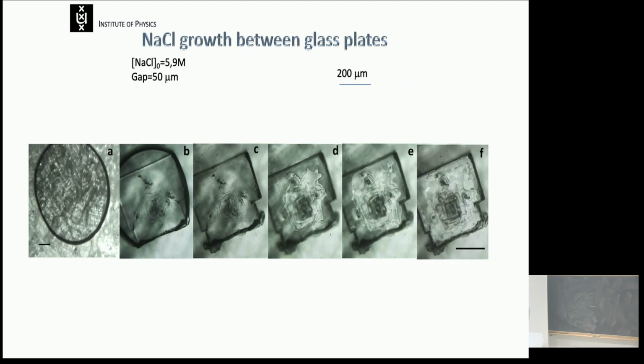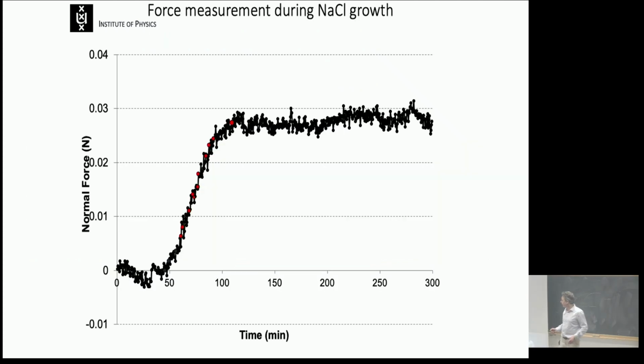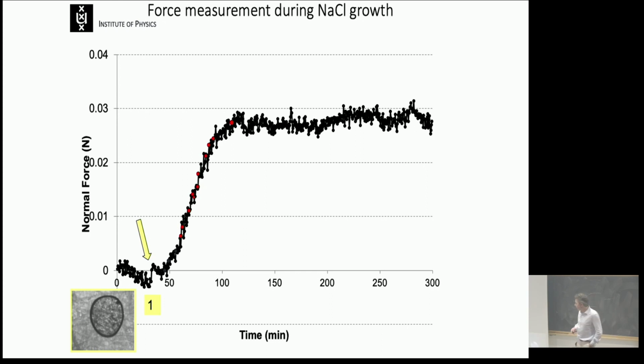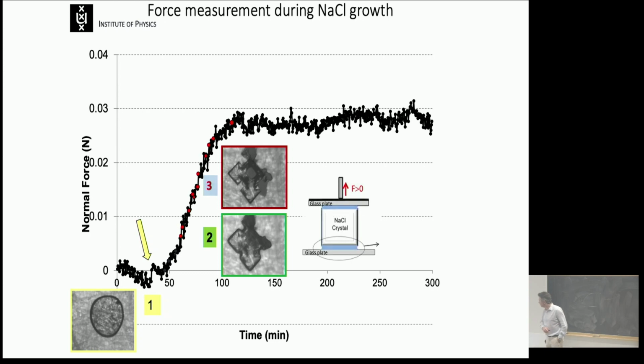This is simple NaCl. And then if we measure the force as a function of time, you see that the moment the crystal almost fills the gap between the two plates, you all of a sudden get a force. That's really cool, but the question was, is there a layer of water? And so if you look very carefully at the images, you can actually see the layer of water, because the image completely changes at the very end of the evaporation. You see the last layer of water evaporating.